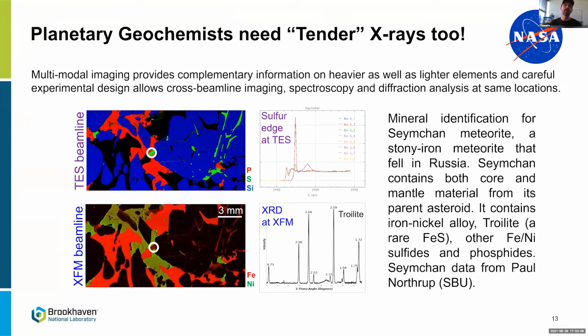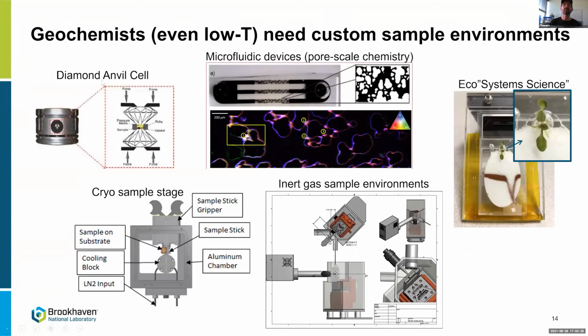This is just one example in planetary geosciences where we needed to confirm a rare iron sulfide mineral in the system that spectroscopy had alluded to. And so we used XFM hard X-ray diffraction to really finalize that identification of that mineral. But a lot of opportunity for geoscientists to do work with tender X-rays.